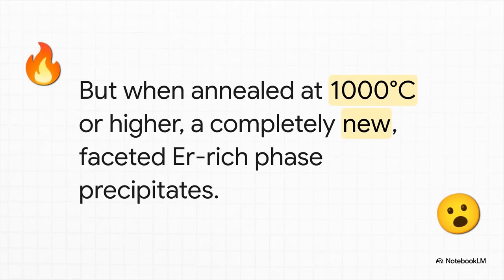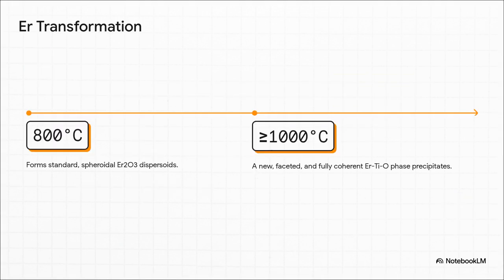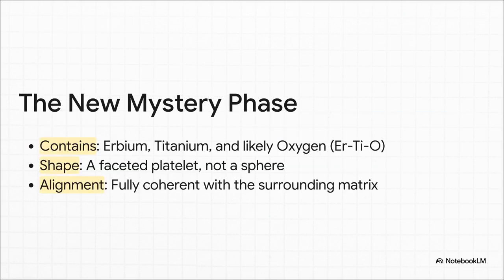But here's where the real mystery kicks in. The researchers decided, hey, what happens if we push the temperature even higher? And this is where the story gets really weird. And what they found was wild. At 800 degrees, you get those standard little spheres we talked about. But when they cranked the heat all the way up to 1000 degrees Celsius, those spheres vanished. And in their place, something entirely new and unexpected started to form. They had discovered a brand new mystery phase.